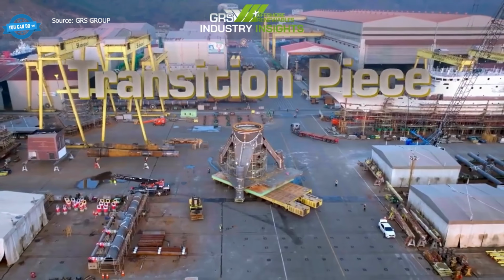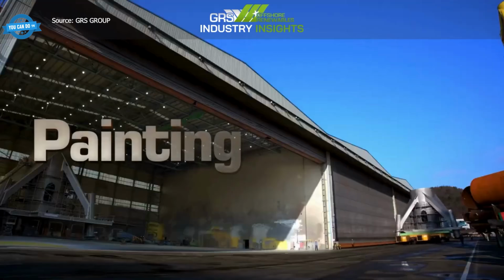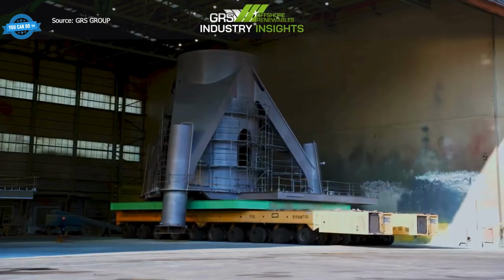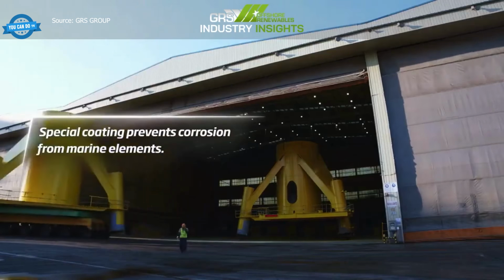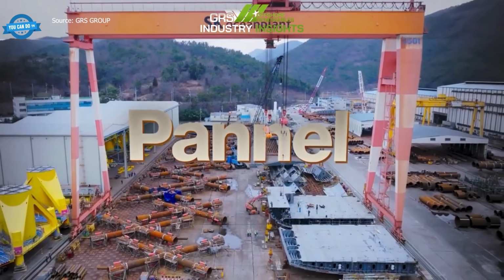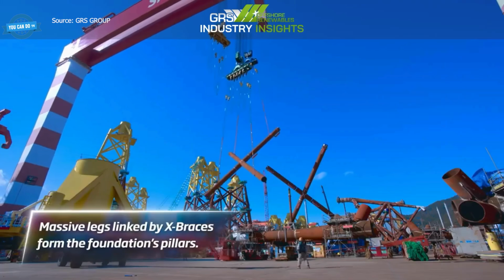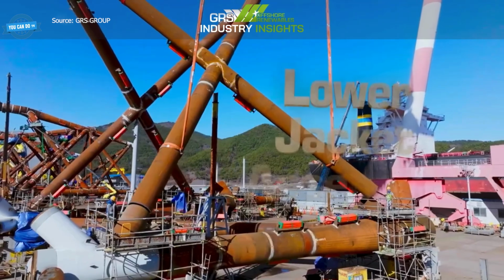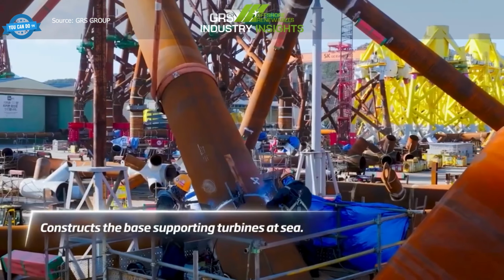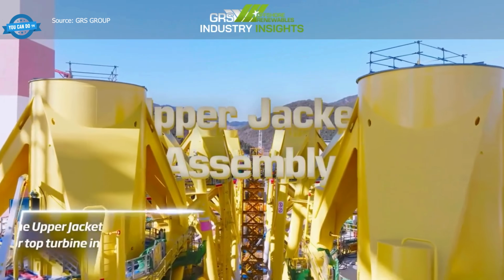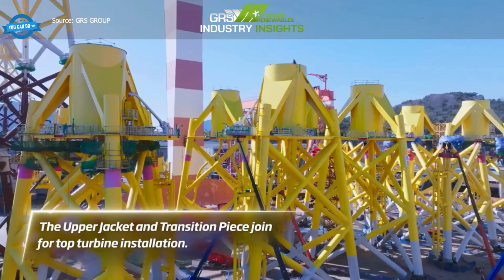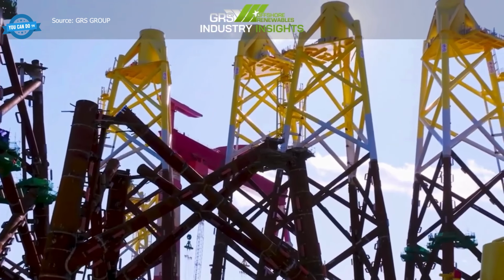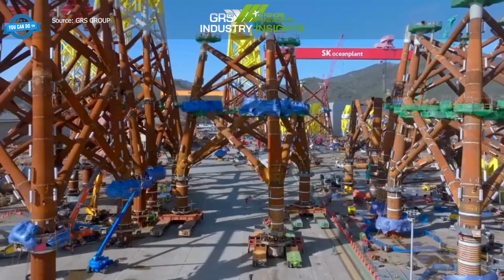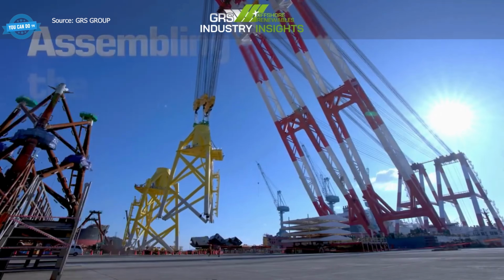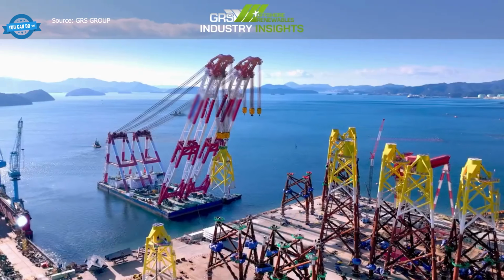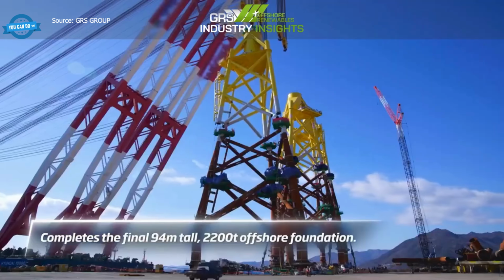Inside heavy fabrication halls, rolling machines gradually curve the steel into giant cylindrical sections, with hydraulic pressure measured in thousands of tons. Submerged arc welding then locks the shape permanently, fusing the seam from both sides in long, controlled passes. Precision matters immediately because these structures may eventually stand 94 meters tall, weigh 2,200 tons, and operate for decades under wave loads, corrosion, vibration, and constant offshore stress conditions, with offshore repairs becoming extremely difficult once they are installed at sea.